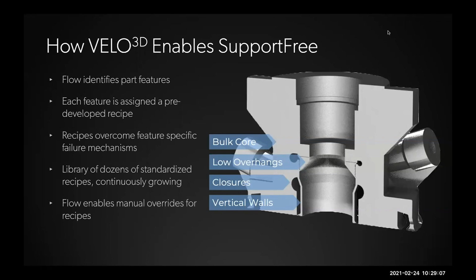I know that a lot of other incumbent systems have struggled with applying these high powers to high throughput systems. There's a lot of soot generated. There are a lot of challenges that come along with this, but we actually do it. Flow recognizes that and applies a high throughput process to that section of the part. It recognizes low overhangs, like in the volute sections where we don't want to add support material, and applies a predetermined set laser parameter to that section such that it prints support free without the need for any support material and also with a very smooth nominal surface finish.